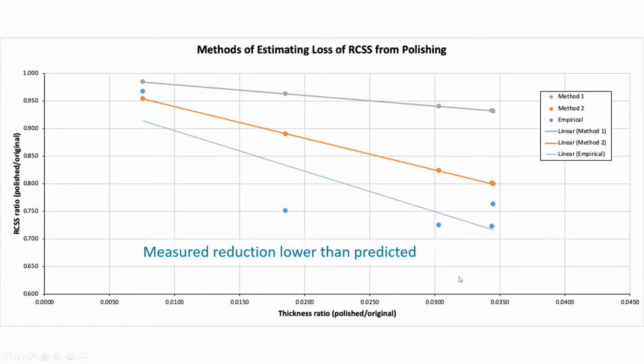It's also worth noting that down here, for this particular project, we had removed almost 1/100 of an inch of glass. Again, this is a ratio, this isn't the actual value. And so we know that we can go that far and still not have excessive distortion, and we can still have reasonable strength. And this was 1/4 inch glass. So if we go thicker, one could probably go even deeper than that, as long as we could limit that distortion, because we don't want to grind a lens into our window, because people are going to notice that when they go by.